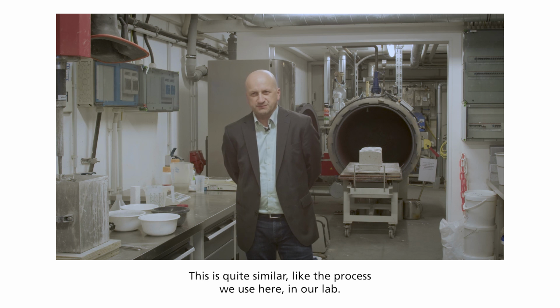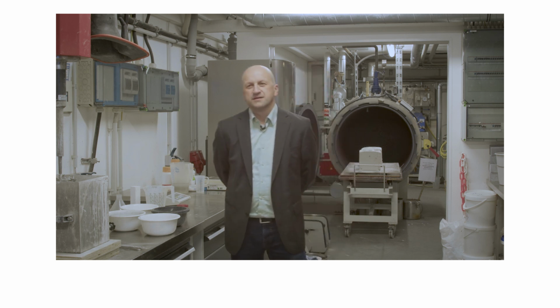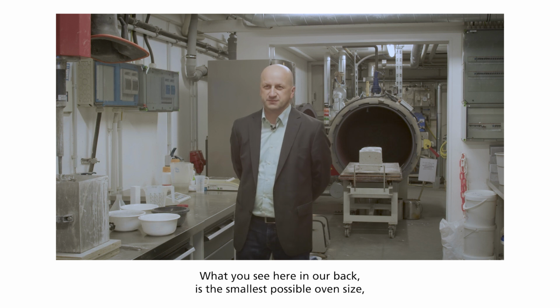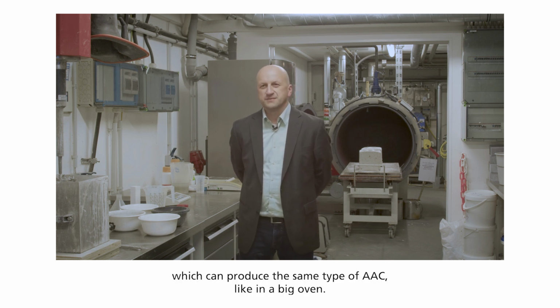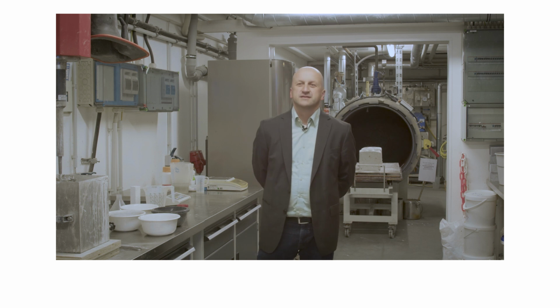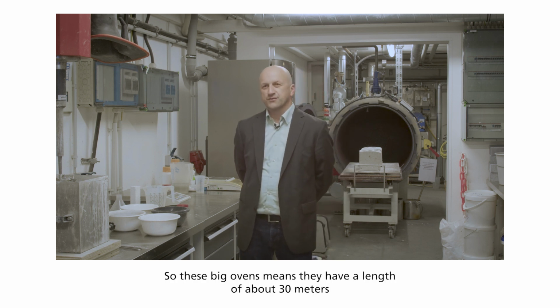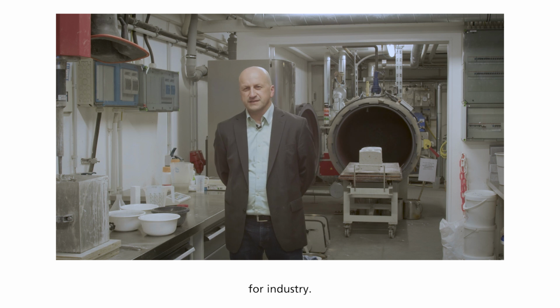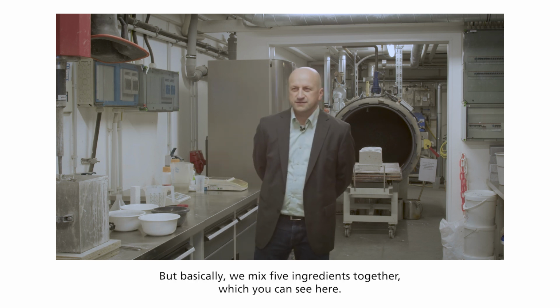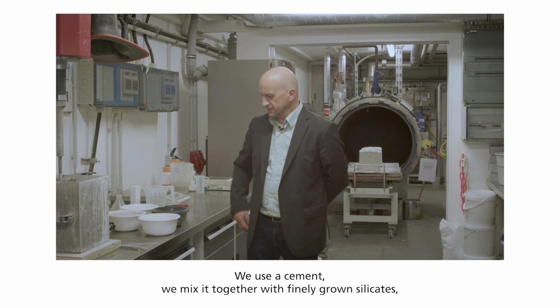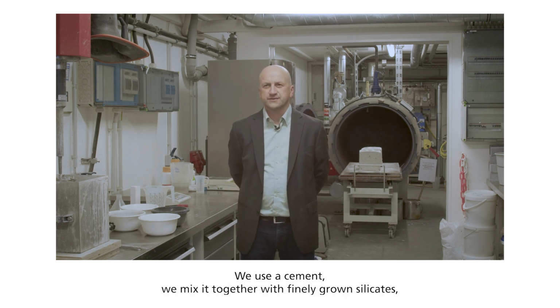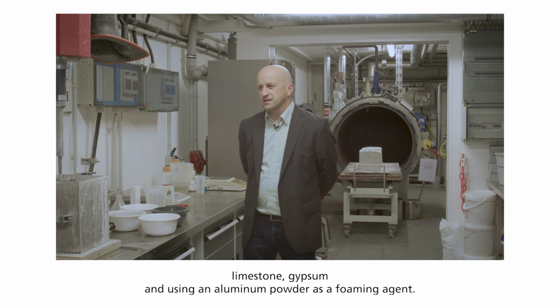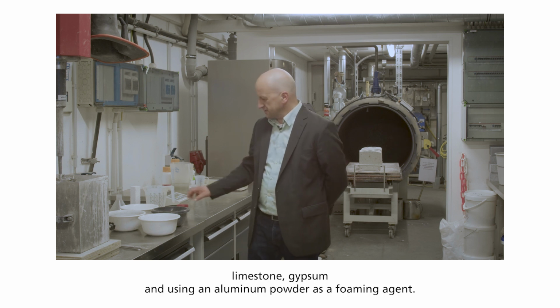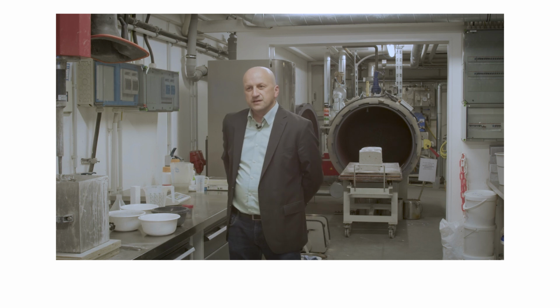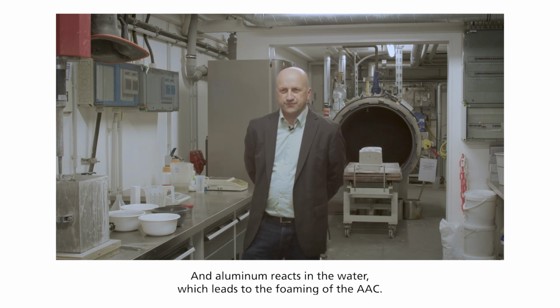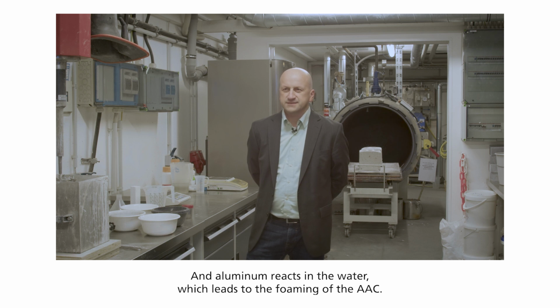This is quite similar to the process we use here in our lab. What you see here in the back is the smallest possible oven size, which can produce the same type of AAC as a big oven. The big ovens for industry have a length of about 30 meters. But basically we mix 5 ingredients together, which you can see here. We use cement, we mix it together with finely ground silicates, limestone, gypsum, and use aluminum powder as a foaming agent. And aluminum reacts in the water, which leads to the foaming of the AAC.